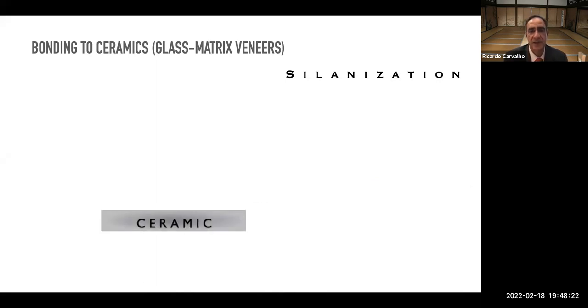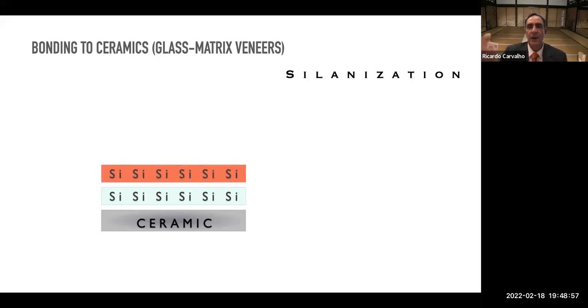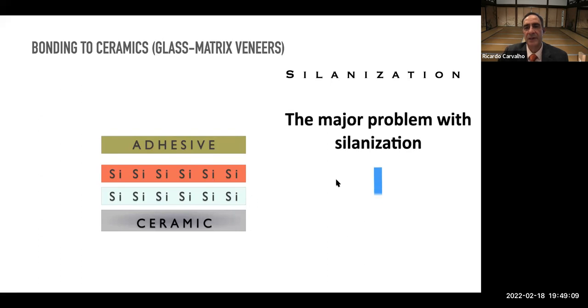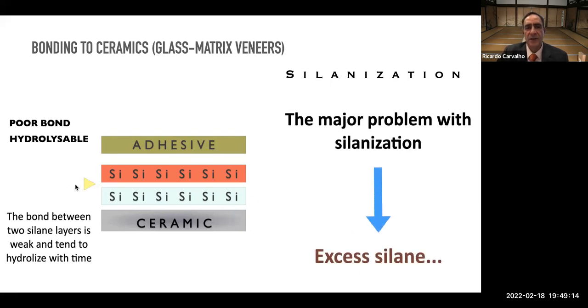But let's say we have the ceramic surface here, and then I come and apply my single layer of silane. That's what I want to happen. Clinically, if I had microscopic eyes, I would like to be able to look at the ceramic surface and see a single layer of silane deposited on the surface. The reason is the bond between this very first layer of silane and the ceramic is really strong. But if I apply way too much silane, we're going to start building layers of silane on top of other silane. And that is the most important issue here, because with excess silane the bonds between different layers of silane are rather weak, and they may hydrolyze with time.